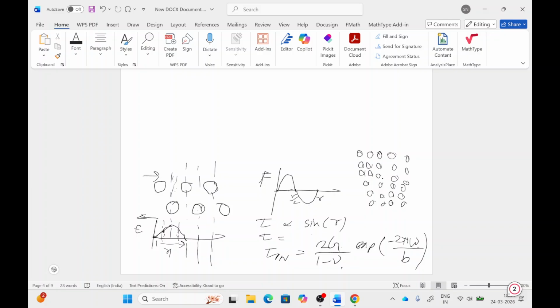So at the top side there are five lines, and at the bottom it is four lines. So the dislocation width which we discussed in the previous lectures, that W is this dislocation width. So in dislocation also we have atoms. When it moves, the friction stress felt by these atoms during the motion of dislocation is the Peierls-Nabarro stress. You can see the derivation for this Peierls-Nabarro stress in the textbooks also.